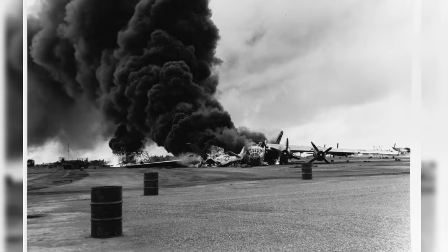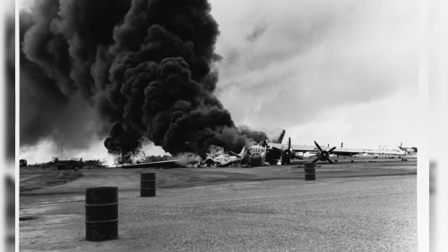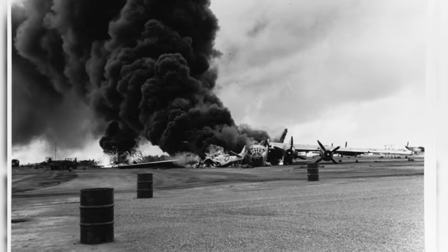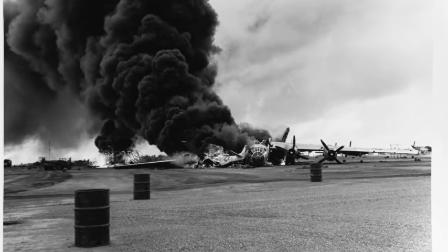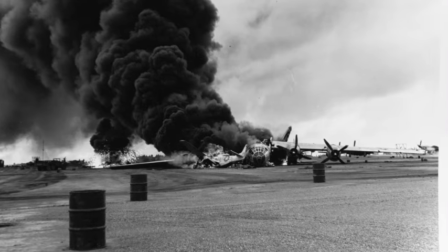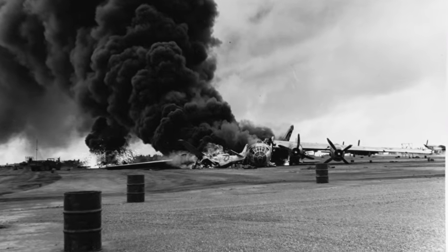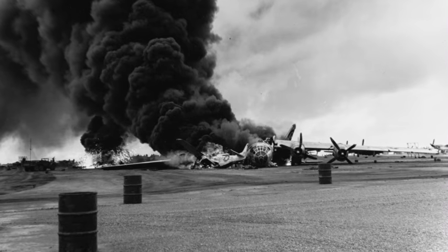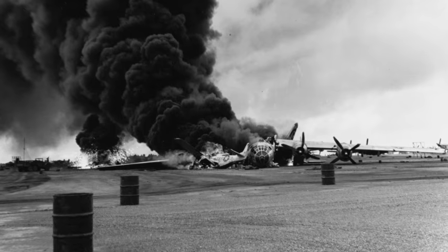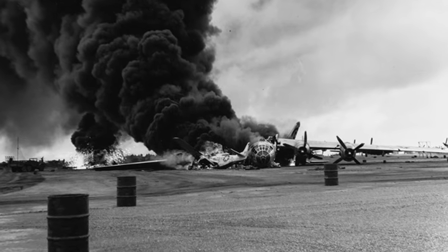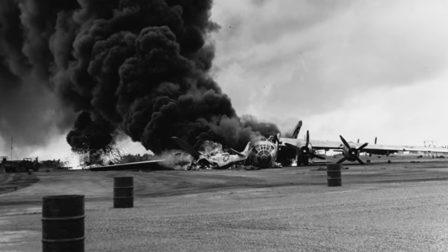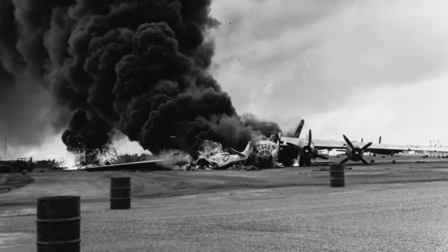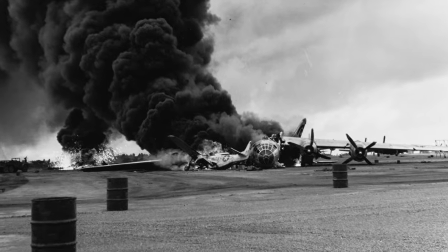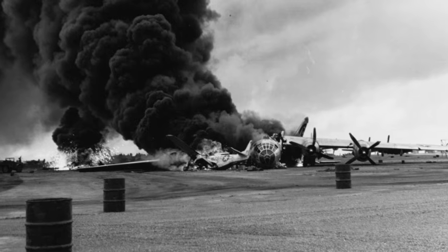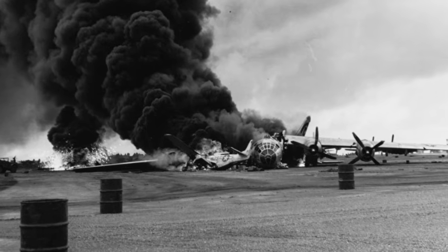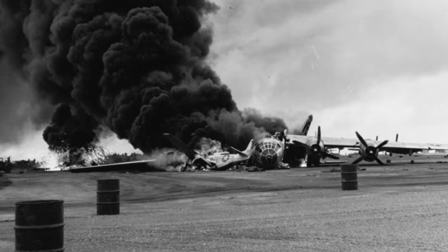The rear row of cylinders, the 9 cylinders at the back of the twin-row engine, received cooling air only after it had already passed over the front row, by which point it was hotter and moving more slowly. The rear cylinders, especially the upper ones, ran dangerously hot. Hot weather and poor runways in the Pacific and in the China-Burma-India theater forced the use of extremely high power settings for takeoff and climb, which generated enormous heat. And the need to close the cowl flaps to reduce drag at high altitude trapped that heat inside the cowling. The combination produced cylinder head temperatures that pushed the engine and the spark plugs inside it past their safe limits.